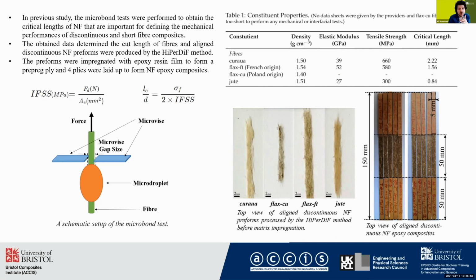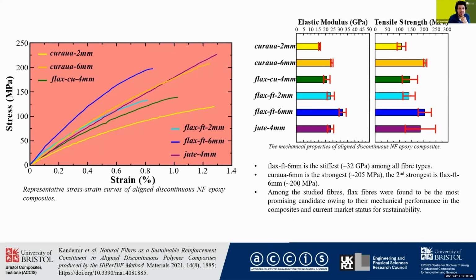Then the preforms were impregnated with epoxy resin to form prepregs. By using 4 prepregs, we produced these composite specimens, and they were tensile tested. Here you can see the representative stress strain curves and the mechanical properties of highly aligned natural fiber epoxy composites.